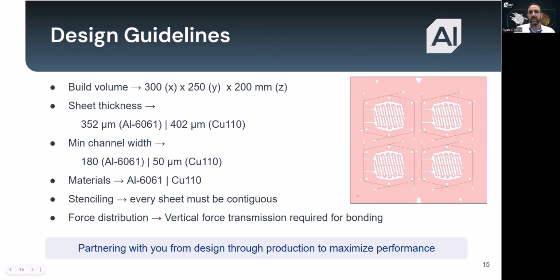Minimum channel width is 180 microns for aluminum and as small as 50 microns for copper. Those properties come directly from the materials themselves, right, and their laser absorptivity. Both of these are extremely fine for liquid cooling and allow us to build high density microcapillary networks that you simply can't produce with conventional manufacturing methods. Right now we're producing parts in 6061 and copper 110, and those materials give us the right mix of mechanical strength, lightweighting, and high thermal conductivity.